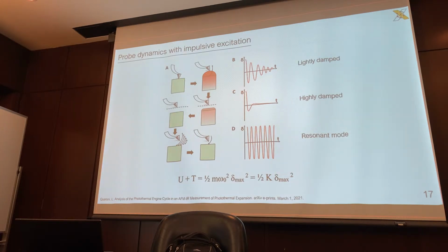I should say that I got similar responses from softer materials as I did with your samples, not necessarily that they're a higher modulus. So for a lightly damped sample, you will see this ring down effect of your deflection as a function of time. For a highly damped material, you're going to see something very different. For softer materials, you'll see an automatic decrease in deflection and then a flattening.